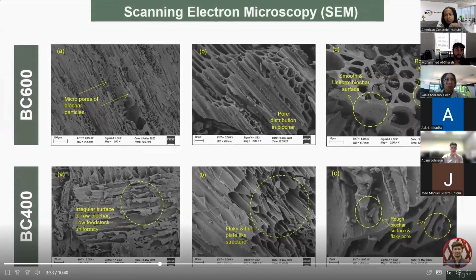In the BC600, the overall structure has uniform porosity. These pores are like rounded honeycomb and the outer surface is smooth. On the other hand, for BC400, the overall structure has low feedstock uniformity. Pores are mostly flaky, thin plate-like shape, and the outer surface is rough.